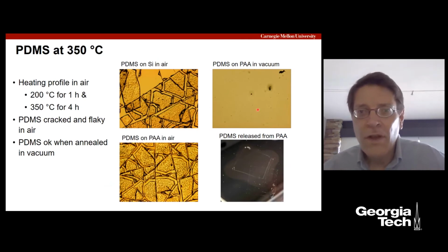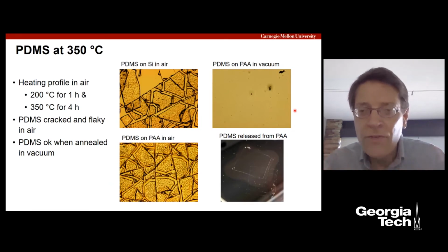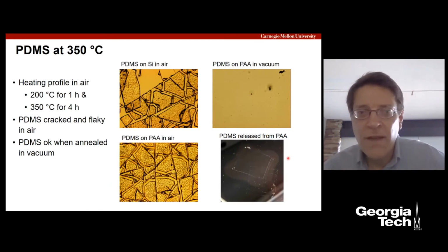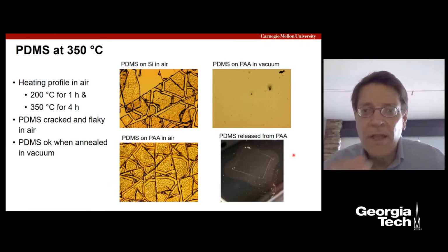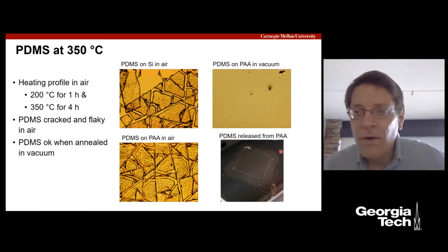However, we did find early on that by putting PDMS in a vacuum or in an inert environment like low vac 1 torr nitrogen, we don't get the cracking. And in fact, it also releases from PAA. We use polyacrylic acid for a release layer. It's actually a very nice release layer for this because it's pretty robust to all the thin film processing we need to do on top, and it releases just in salt water. So quite nice.